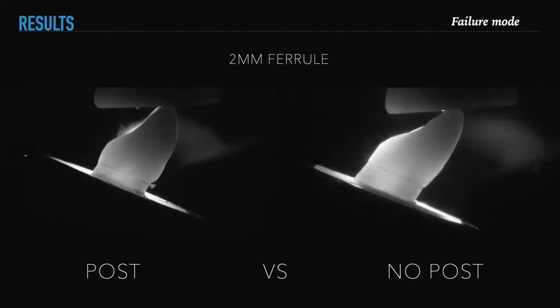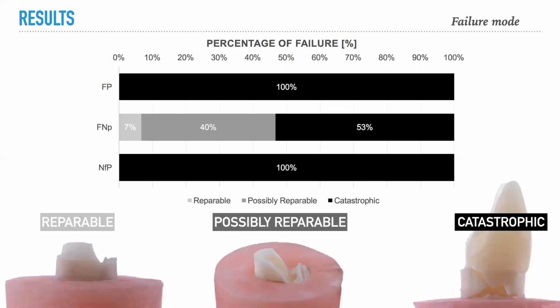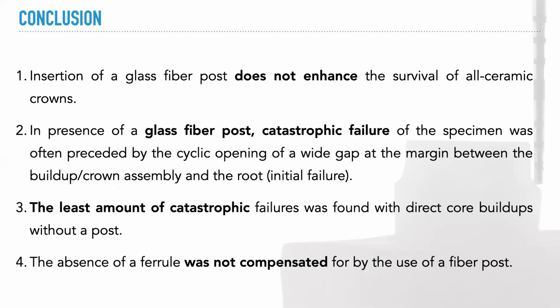So the percentage of failures, here we can see the failure mode. Groups with fiber post showed 100% of catastrophic failures, while the no post group presented 47% of non-catastrophic failures. So the conclusion of this study is that insertion of a glass fiber post does not enhance the survival of all ceramic crowns.